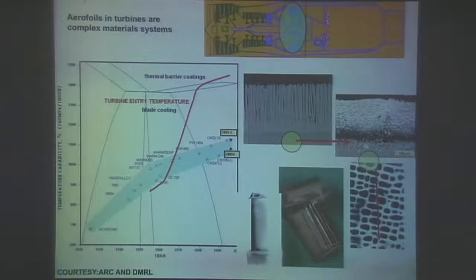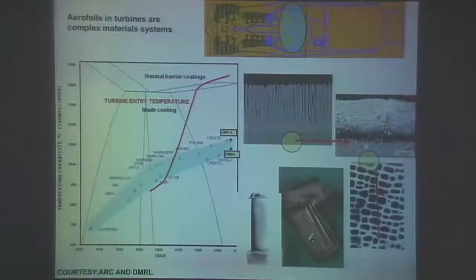It's an extraordinary material system when you remember that these parts are rotating at 10,000 revolutions per minute at temperatures of 1,500 degrees centigrade in an oxidizing atmosphere, subject to a variety of alternating loads, and you're dealing with a thin-walled system, about a millimeter thick in places, of nickel-based superalloy, which has an aluminide coating and an intermetallic coating, on top of which is a ceramic coating. So you can imagine the extraordinary challenges that come about in engineering such material systems, and indeed the design of such material systems in aircraft today. And I'll talk a little bit about safety in aircraft a little bit later on.